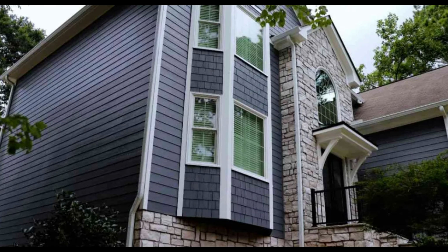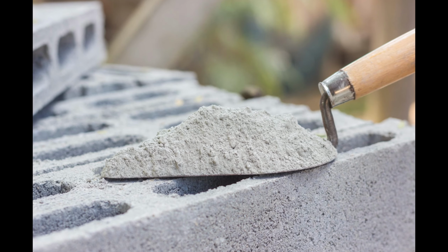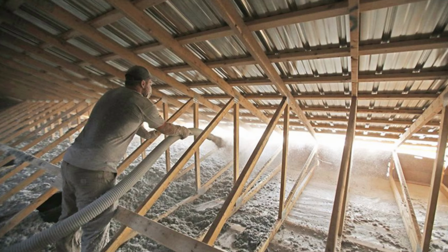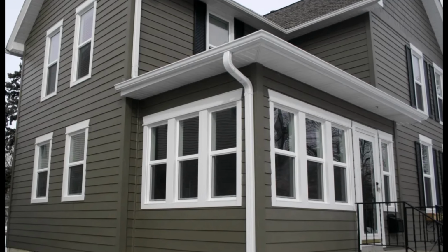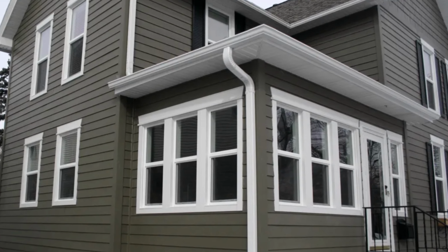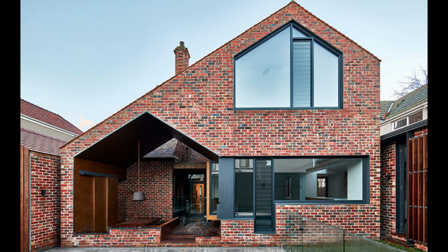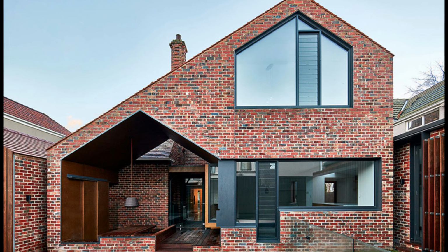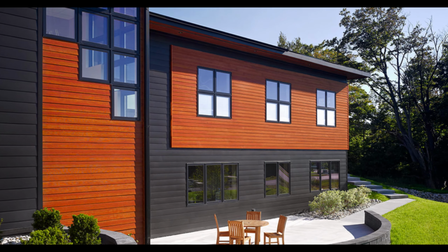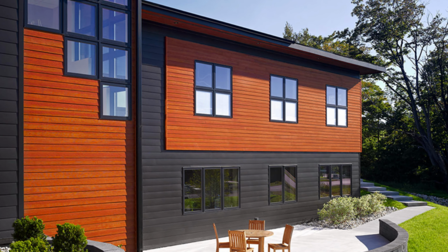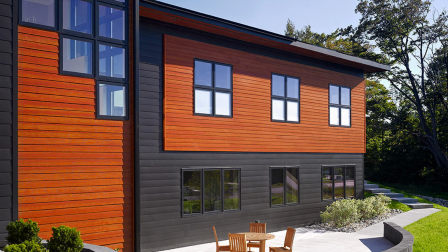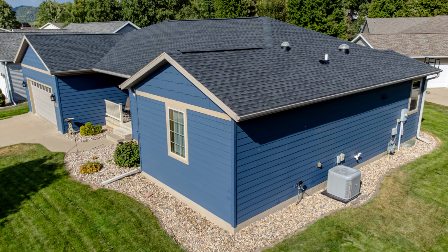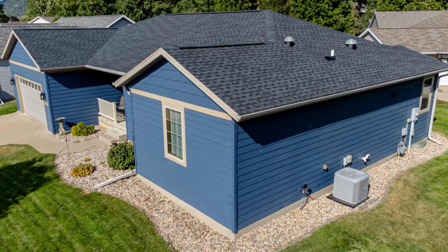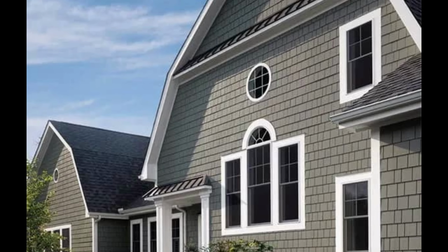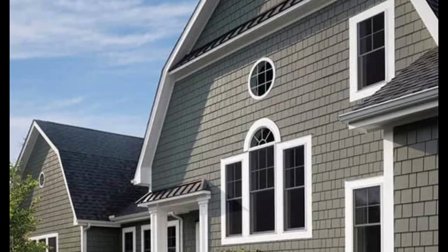Material number 2. Fiber cement siding. Fiber cement siding is manufactured from cement, sand, and cellulose fiber. It resists water penetration. Fiber cement costs $8 to $12 per square foot installed. Vinyl siding costs $3 to $6 per square foot. Vinyl degrades after 15 to 20 years. It becomes brittle, cracks, and warps. Fiber cement siding functions for 50 years or longer without degradation or replacement.